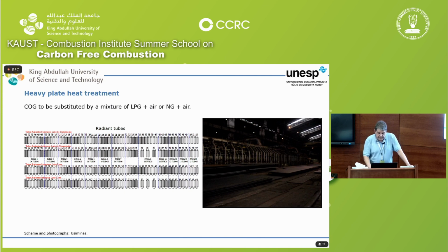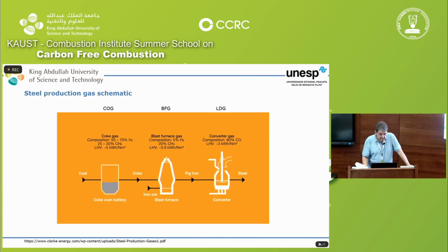Coke oven gas, as you see here, has about 60% of hydrogen. And this amount of hydrogen makes it a fuel that anchors in the burner. It becomes stable because of the amount of hydrogen. You saw yesterday or the day before yesterday that hydrogen has a very high flame velocity. So it's easy to anchor any flame with hydrogen. In one of our experiments, we had a free flame of methane, and we used only 3% of hydrogen.